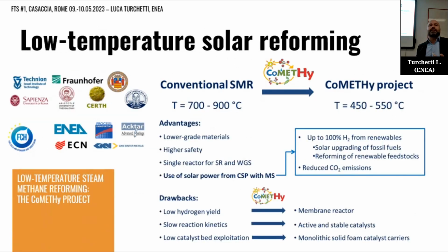So how can we feed this process with solar heat? I will focus on the use of solar salt, which means a mixture that can be heated, as we said before, up to 565 Celsius degrees as bath temperature. I'm going to report about the experience of a research project that was concluded some years ago and coordinated by ENEA. The project was called CoMETHy, and the aim of this project was to power steam reforming with solar energy, which in the first place requires lowering the operating temperature of reforming, because otherwise we won't be able to couple it with the solar source, with solar salt. So the aim then is to shift the operating temperature window to the range between 450 and 550 Celsius degrees.